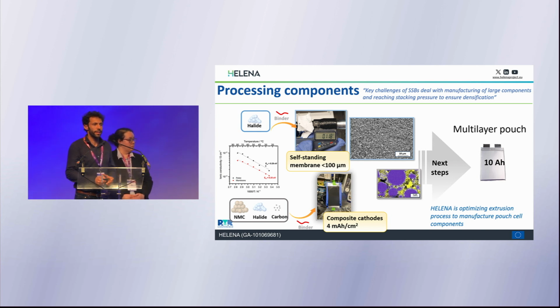You will have details on the electrochemical performance in publications that are coming out of this project that will be listed later. And here what I can say is that now we are at the stage of fabricating these self-standing membranes. So we now have thin self-standing membranes of 100 microns, but we are able to decrease further. So hopefully we will reach the target of the project of 30 micron. In parallel, there is also a lot of work on making the composite cathodes with NMC and the halide. And we are now at the step of making the multi-layer pouch cells. So partners involved in processing with extrusion are now investigating how these materials can be processed.